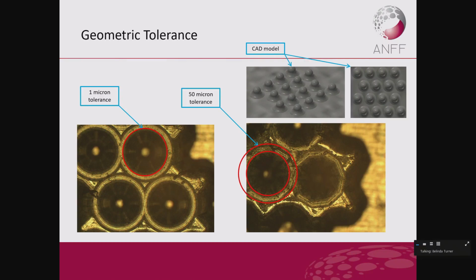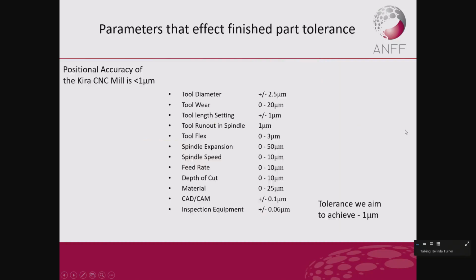And here we've got the same CAD model, same features, but we just put a 50 micron tolerance on these little parts. So the tool stayed within this 50 micron band, and you get this truncated feature. If we put a 1 micron tolerance, it stays within 1 micron of the diameter. So there's lots of different things we can put in to get better quality results, but it all depends on what the customer wants. So we're trying to achieve 1 micron accuracy, but all of these things come into play.